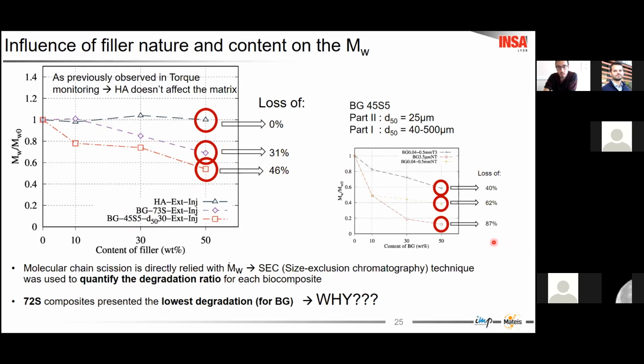We can compare the results with those of part 1 and see that for the 45S without thermal treatment, there was a loss of molecular weight of 62%, and in our study it was 46%. This difference is mostly due to the use of a process that's a direct injection, so we reduce the time at high temperatures, and so we reduce the degradation.